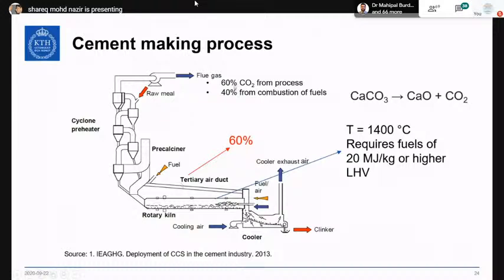Now, as we see here, 60% of the CO2 comes from the process itself. That is from dissociating calcium carbonate into calcium oxide and CO2. So this CO2 is coming from the process chemistry and not from burning the fuel. Whereas the remaining 40% of the emissions comes from the combustion of fuels in the kiln. So we cannot go away from dissociating calcium carbonate. So we have to deal with this CO2, that is 60% of CO2 coming from the process. But then this 40% is something that we can play around with. But again, we can play around with it to an extent because we still need fuels with higher lower heating value.